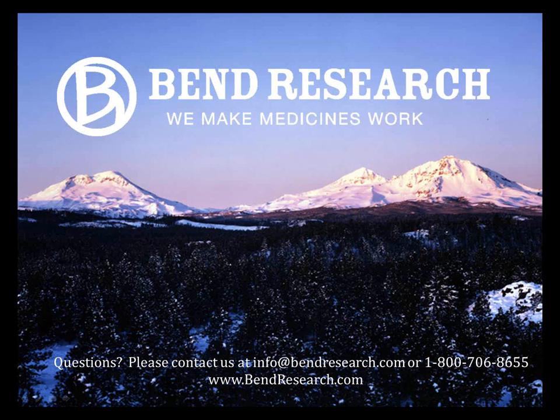And what's important there as well is developing a high Tg formulation that can tolerate the outlet temperature, which is usually the highest temperature observed by the biotherapeutic. We usually rationally develop these formulations with small molecular weight sugars as well as, say, a polymer, to develop a higher Tg material so that we don't see mobility at, say, a 60-degree outlet during a jar collection. The biotherapeutics themselves often have Tgs in the dry state around 190, 200 degrees Celsius. So we really are seeing a stable product and formulation using these conditions during collection using spray drying.